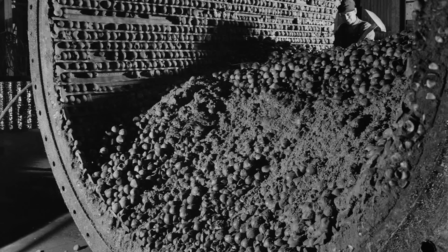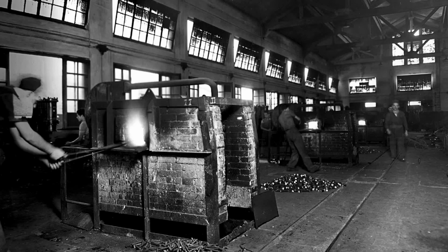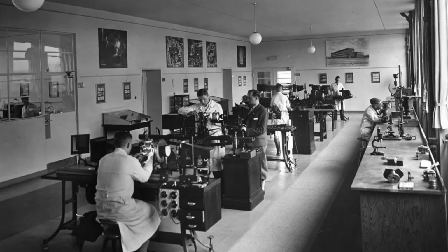A recipe that says tungsten carbide plus cobalt sounds simple. Industrial reality was not. The size of the tungsten particles mattered. The carbon content mattered. The purity of the powders mattered. The percentage of cobalt mattered. How thoroughly the powders were mixed mattered. Pressing pressure mattered. Humidity could matter. The sintering temperature mattered. How quickly the compact was heated mattered. How long it remained at temperature mattered. How it cooled mattered. Tiny variations at any stage could produce a material with different hardness, different porosity, different toughness, and completely different behavior in a cutting tool.